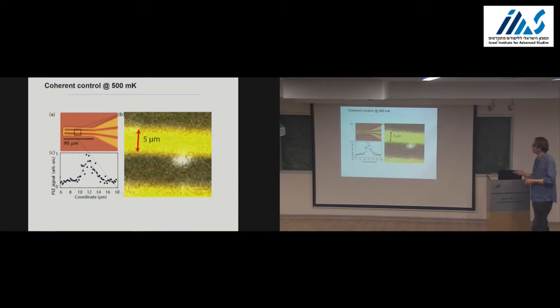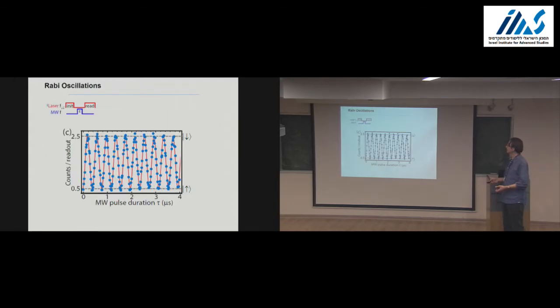So now with this design in place, you can send microwave pulses, rotate your atomic spin, and then measure it optically. This is the result of this experiment, where the resonant microwave rotation pulse was varied in time, and now you see the Rabi oscillations of the single electron spin with high contrast, which don't show any significant decay on a microsecond time scale. So it's already longer than what I was mentioning before. We don't see any decay.